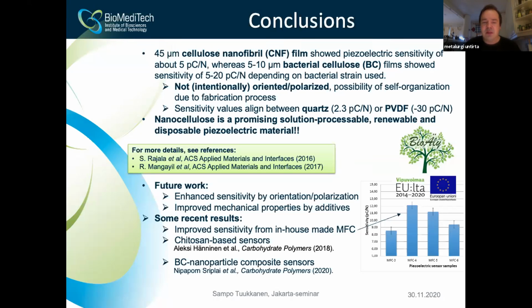Actually, Nipaporn, who worked in my lab, started from the growth of the bacterial cellulose film, and then she put this wet bacterial cellulose film there, and then she grew these manganese oxide particles so that they go inside the film somehow, forming the composite. Yeah, I'm not a chemist. I cannot say much more about the details, but it was quite high level chemistry. The results are quite interesting also. You can check the paper. It's a new one, of course.